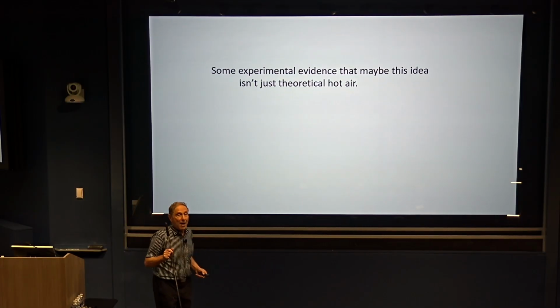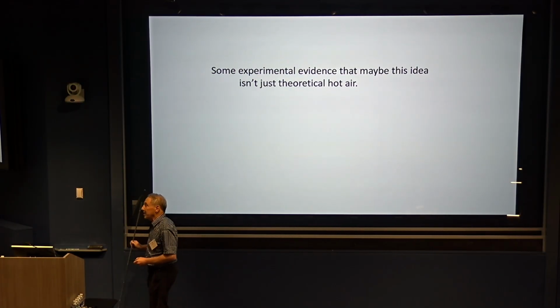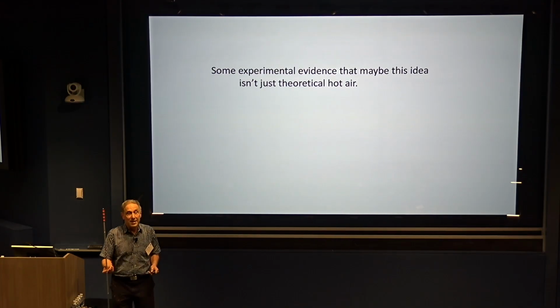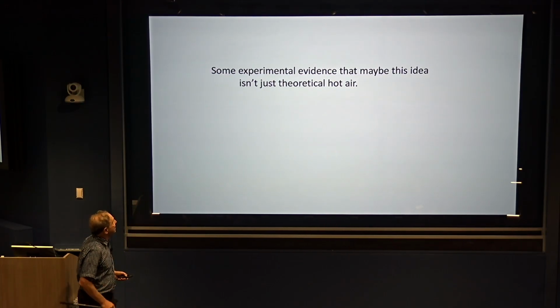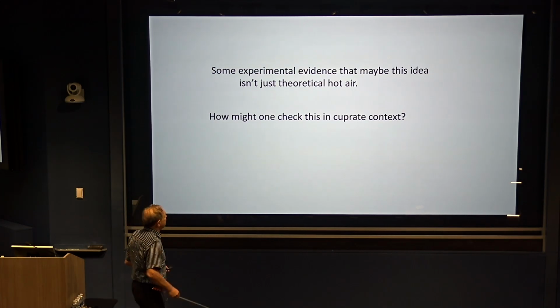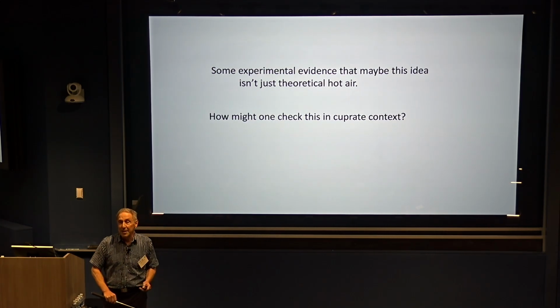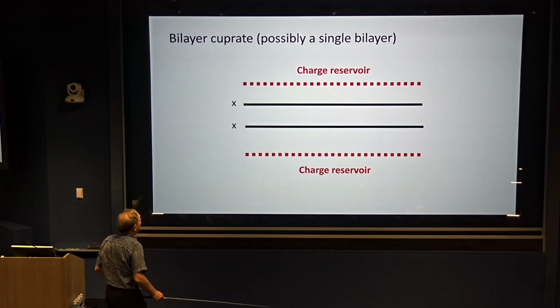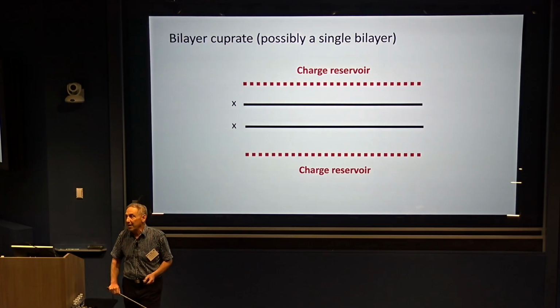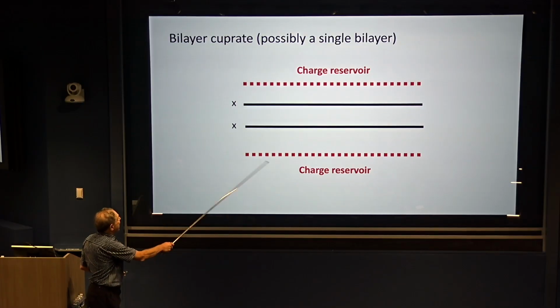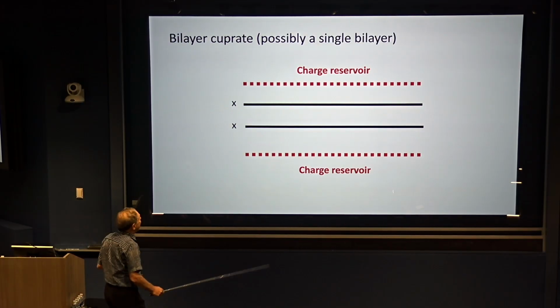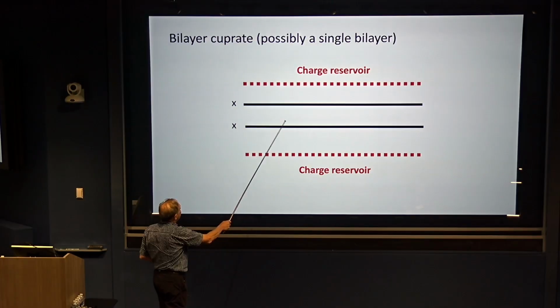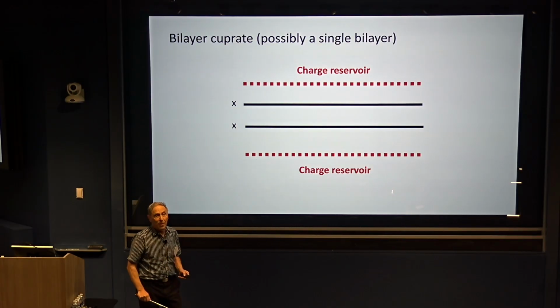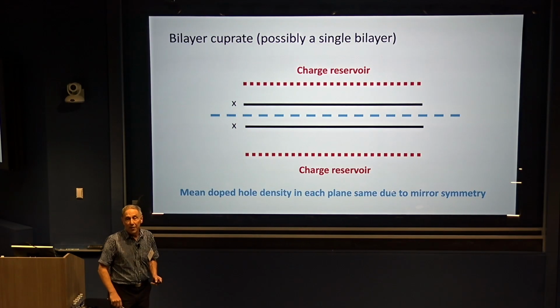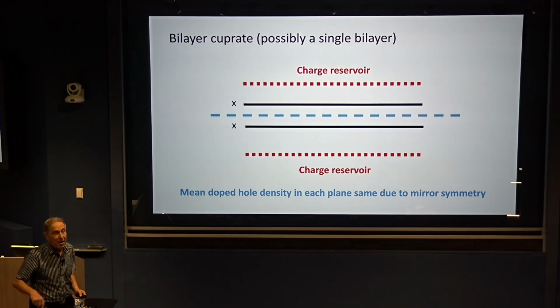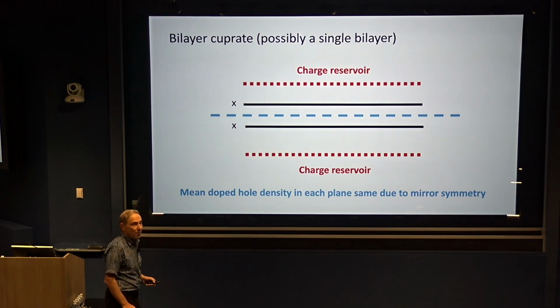So now let me try to present some experimental evidence that this is not just a theorist's fantasy. So how would we check this in the cuprate context? So the best way to do it, which hasn't been done, would be the following: to take a bilayer cuprate, and the bilayer cuprate, all the ones that we typically study have a mirror plane, and therefore the doping concentration in the upper layer and the lower layer are equal to each other.